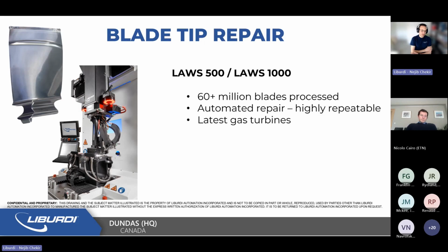As an example, one very common example is blade tip repair of high pressure compressor blades. In this case, you can see it's a LAWS 500, but we have sold LAWS 500 and LAWS 1000 platforms to be able to achieve these type of repairs. And what you see here is the plasma arc welding process on the left side, two repair stations. So when one is welding, you can load the other one as needed. Wire feeding solution, top cameras to be able to generate the sites of interest. And this solution pretty much was integrated in the first machine that we sold for this type of application was in the early 90s.